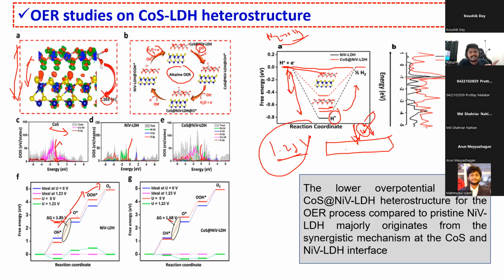In contrast with the battery, in the battery we found that if it is very close to the Fermi level, it will have a very high adsorption energy, and then it can prevent the shuttle effect. But here, hydrogen should be adsorbed in a moderate range so that it can adsorb and later desorb from the surface. So you can see that for the pristine nickel vanadium LDH, the value is around 1.093 from the Fermi level. But after making a heterostructure, the value changed to 1.240. Basically, it's moving farther from the Fermi level. So as I told previously, the farther from the Fermi level, the weaker the binding energy is.